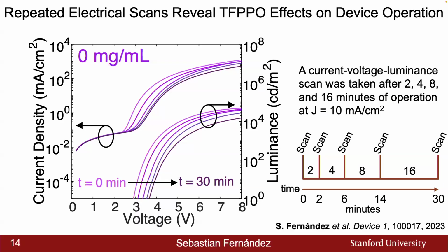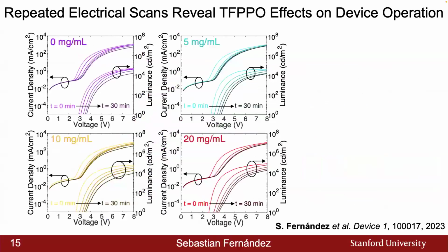And graphically, this can be shown here as to how we can get 30 minutes of total operation at 10 milliamps per centimeter squared, equating to 5 scans that we can take from these devices. And so there are various optoelectronic parameters that we can now start to probe under identical operating conditions. And we can look at them together across TFPPO concentration.